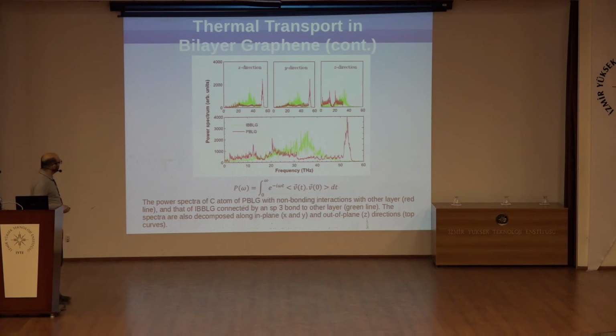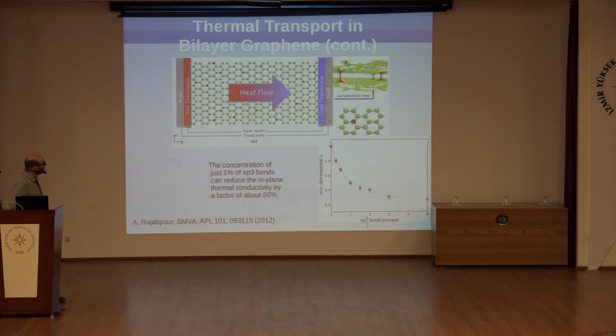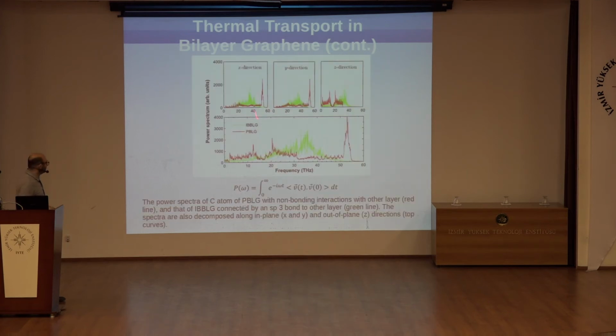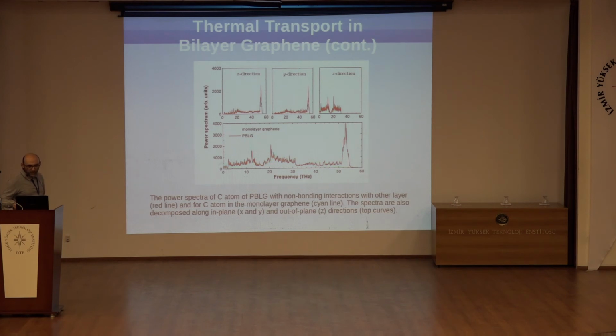To understand what is going on inside the system, it is possible to investigate the vibrational density of states in the case of pure graphene, pure bilayer graphene, and bilayer graphene with hydrogenation. By creating these sp3 bonds, it is possible to break the in-plane thermal transport and change it. As you see, this is pristine, and this is with sp3 bonds; the thermal conductivity decreases due to the amount of scattering induced by some sort of defects.